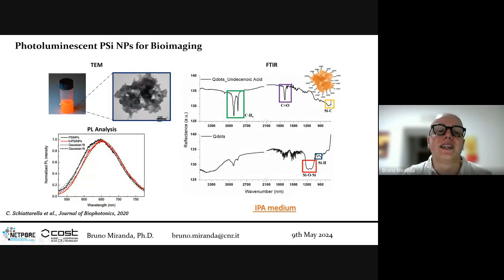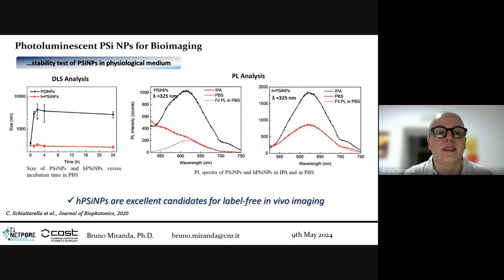This is the typical suspension we obtain that is very photoluminescent under UV light, and we quickly performed some stability tests. We performed hydrosilylation on these porous silicon nanoparticles. While the porous silicon nanoparticles exhibited an increase in size, meaning they were aggregating in the medium, and their photoluminescence was quenching over time, the hydrosilylated porous silicon nanoparticles remained very stable in size and in photoluminescence, also in PBS.